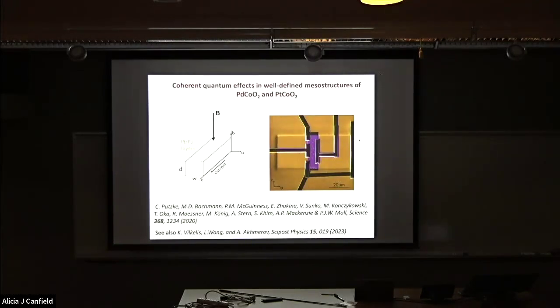So now the thing I'd like to close with, and we have theorists in the audience, I think this is really not something we'd anticipated, and certainly not something that we fully understand. We did an experiment where we wanted to measure the C-axis conductivity in FIB devices. So we made a FIB device where the planes were running across the plane of the channel, so that we're passing a current from here to here, and this is a direct measurement of the C-axis voltage drop. It's a very good way compared to standard ways of measuring C-axis conductivity in layered material.